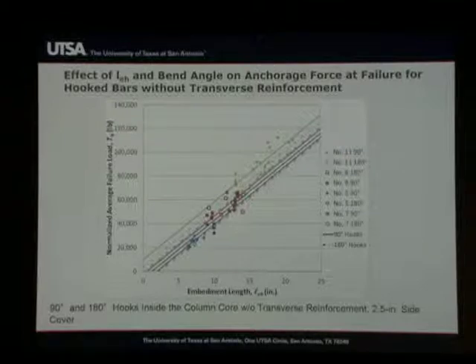This graph shows the effect of embedment length versus the bar force. That's a quantity that we like to use as a measure of anchorage strength, is the force in the bar, not the stress. This is the actual pull-out force in the bar. And all this graph is really intending to show is that when you look at bar force versus embedment length, and we know this from splice tests and development length tests and straight bars, you tend to see a linear trend. That bar force varies linearly with embedment length. In this case, maybe you see somewhat of a nonlinear relationship, but for the purpose of design provisions, maybe it is appropriate to account for that as a straight line, and that would be fine.